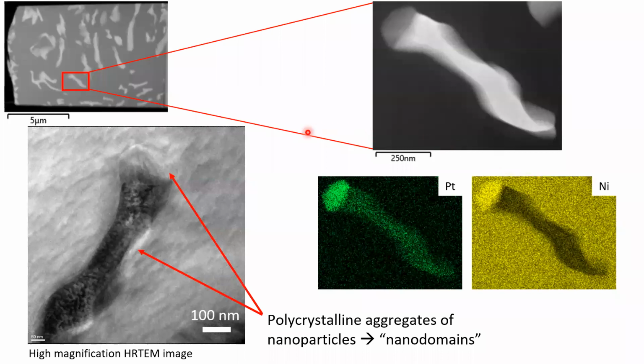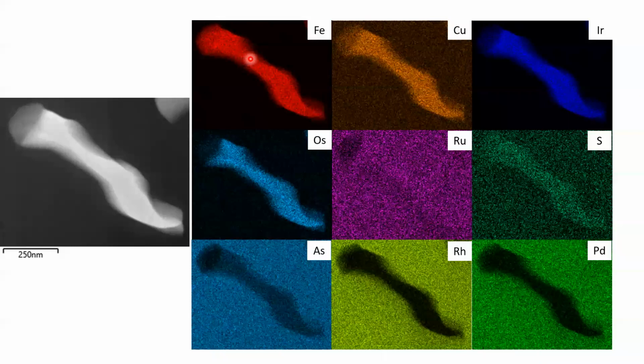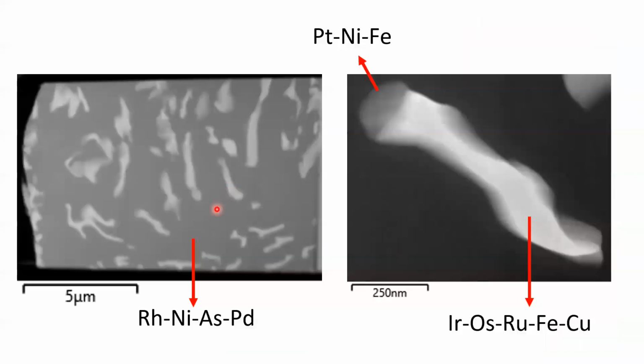Here we also studied one of these intergrowths. And this is a high magnification, high resolution TEM image, and shows that this intergrowth is mainly made of an aggregate of nanoparticles. And there are different domains that can be seen here in this elemental mapping, which shows the upper part is mainly made of platinum, nickel, some iron, and the lower part is made of iron, copper, iridium, osmium, and ruthenium. Summarizing, this is the composition of the matrix: rhodium, nickel, arsenic, and palladium. And the composition of this intergrowth is platinum, nickel, iron, and iridium, osmium, ruthenium, iron, and copper in the lower part.